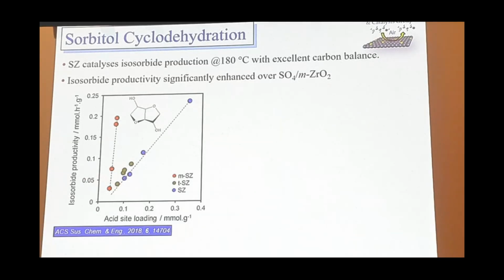The monoclinic zirconia, however, seems to give you a much higher activity. And what we believe is this is due to the nature of the sulfate species on the surface being very different on the monoclinic surface.